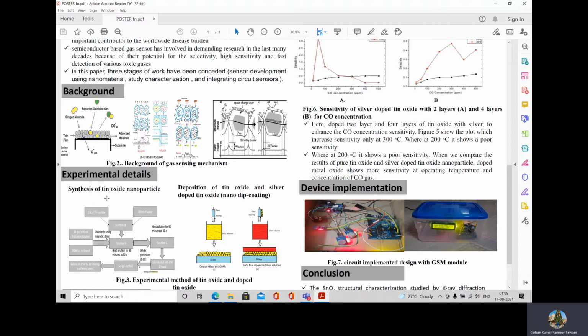If you see here, I first synthesized tin oxide material using tin acetate and water. I made a solution A, and I made sodium hydroxide and methanol as solution B, mixed them together and stirred at a certain temperature. I formed the solution and calcinated it at 600 degrees Celsius for 2 hours, and finally I used a sol-gel method to get a liquid kind of tin oxide and placed it aside. Here the dip coating technique is used.